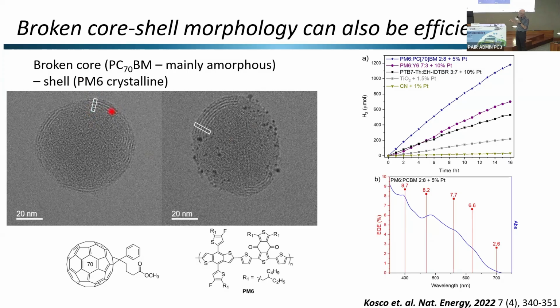So hope you can see this here. This is a very nice illustration of our shell, the PM6 donor. It forms these concentric lamella, and then we have a more amorphous core. This is PCBM. Interestingly, you'll see that the platinum, which is photo-deposited, only deposits on the acceptor. So if you want to know where your acceptor is, you just look at a photo-deposited nanoparticle, and you can see quite clearly it's not forming on the donor at all. So this is a broken core shell here and here, but only on here.